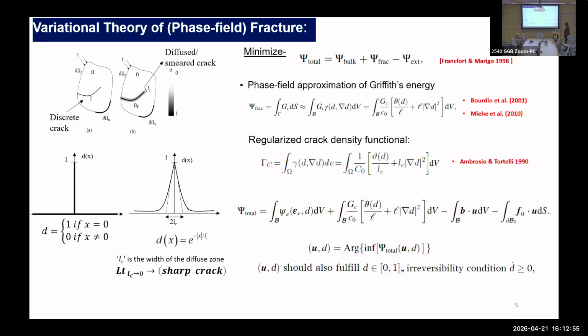So now jumping into the core description or the theory of phase field, which basically started as the formal variational theory of fracture, and the seminal work was by Francfort and Marigo in the late 90s, who recast Griffith's statement of energy balance in the form of energy minimization. So you can write the total energy of a cracked body, which contains the bulk stored elastic energy, and then a fracture energy term, which is balanced with the external work. And then if you can minimize this energy somehow, the propagating crack path emerges naturally from the solution of this minimization problem.